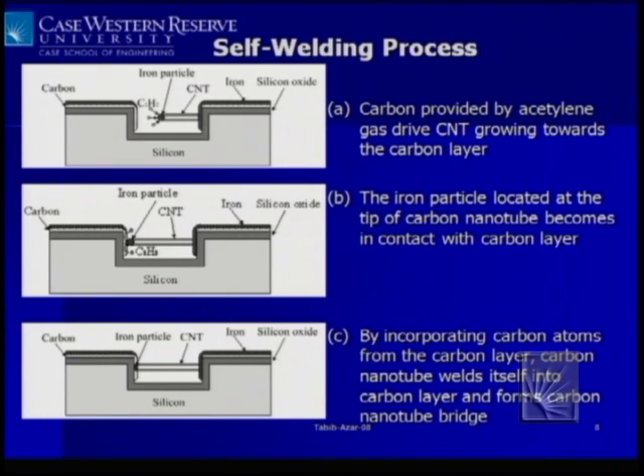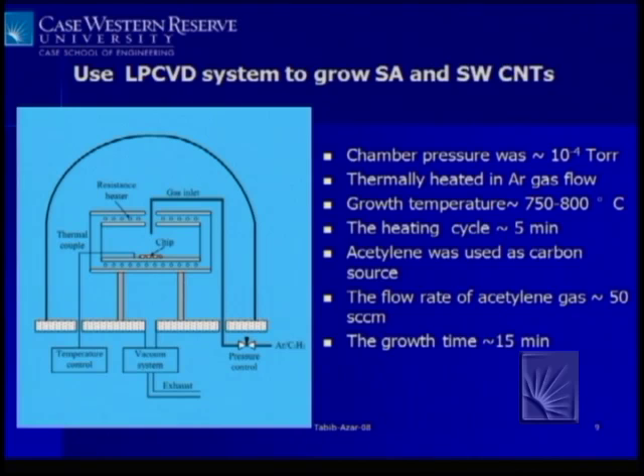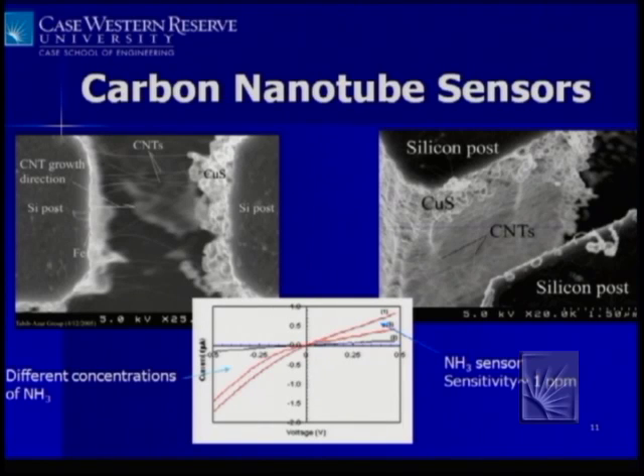The interesting thing about growth is that you can't really dictate when it starts, but as soon as it starts, it goes very fast. So typically, what we do is we set the temperature and the flow rates as indicated in order to start growing these things, and this is an example of what we end up with. We have done it in 10 minutes, but most of the action happens in a fraction of a second. But you have to put it in there and wait for things to start happening, and that we can't dictate. At least till now, we haven't been able to dictate. So the whole thing happens very quickly once it happens.